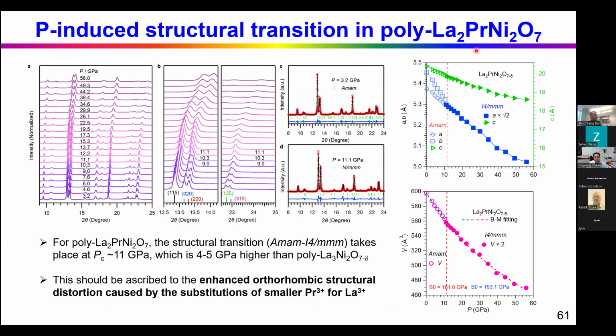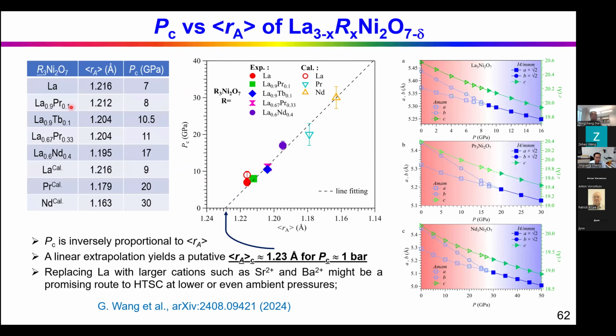And for this Pr doped sample, the structural transition takes place at 11 GPa, which is about 4 to 5 GPa higher than the undoped sample. Basically, we performed the high pressure XRD on each sample, and we determined the PC for the structural transition. We found that the critical pressure for the structural transition increases with reducing the A-site cation size. We also did the calculation, and the result is similar. When you reduce the size of the A-site rare earth cations, the transition pressure increases very quickly.